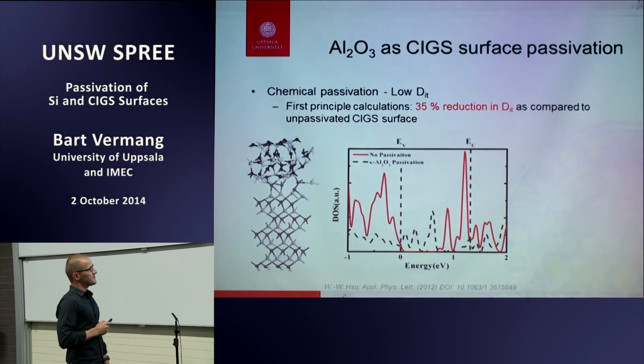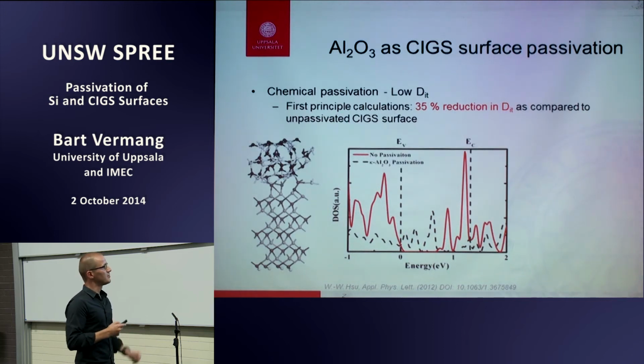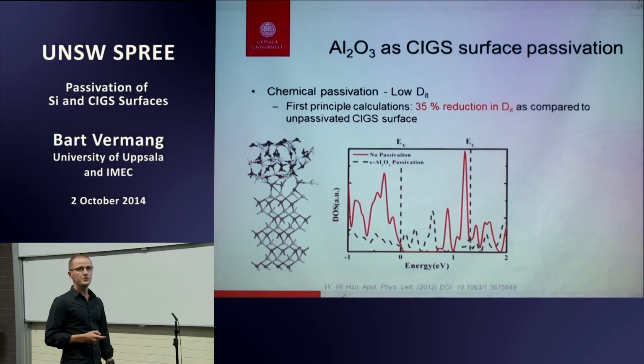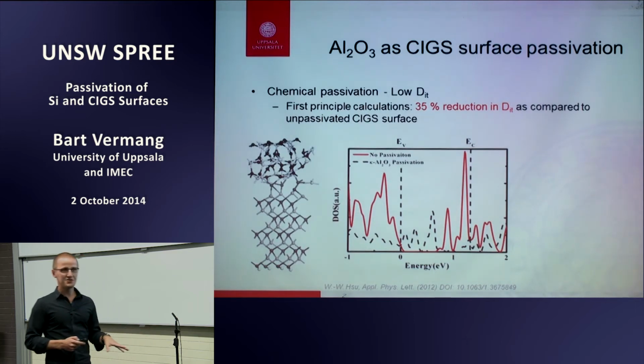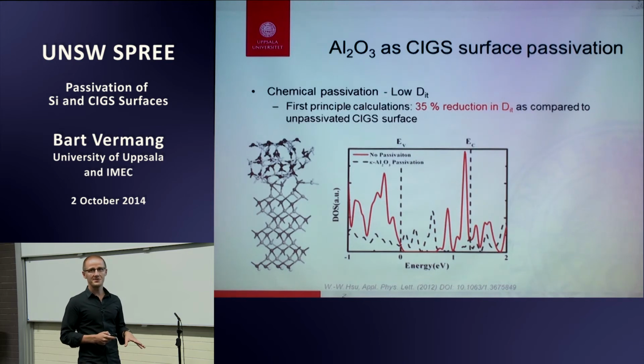So, aluminum oxide as CIGS surface passivation. In the end, the main message is it acts in a very similar way as it acts as silicon surface passivation. First of all, you can reach a low interface trap density by growing an aluminum oxide layer on top of the CIGS absorber layer. Here you see some first principle calculations done by Hsu, and he calculated that you can reduce the Dit within the whole band gap by around 35% by growing this aluminum oxide layer on top of it. I'm using calculations here because it's very difficult to measure. CIGS is a great semiconductor for solar cells, but it's a crappy semiconductor in the end. So to really make measurements on CIGS, it's not that easy.